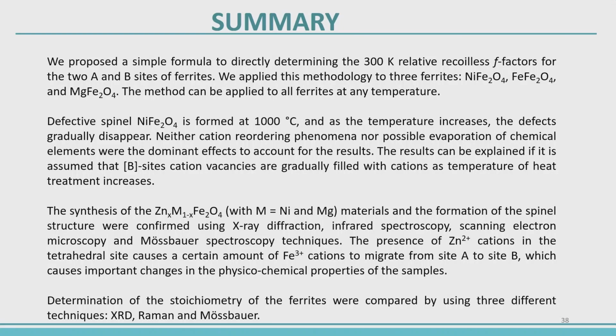The second work that we show here: we think that nickel ferrite is formed at this temperature, 1000 degrees Celsius, but as the temperature increases, the defects gradually disappear. Neither cation reordering phenomena nor possible evaporation of chemical elements were the dominant effects to account for the results. I hope this analysis is right. The results can be explained if we assume that the cation vacancies on the B sites are gradually filled with cations as temperature increases, and this is the third result.